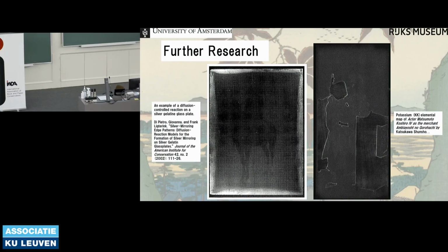Another interesting point is the actual source of the haloing pattern observed. Further testing is needed to determine what is happening. I have two hypotheses. It could be a diffusion limited reaction causing some sort of pattern similar to the one seen here on this silver gelatin print, silver gelatin glass plate. Or it could be some sort of reaction taking place with the black sumi ink that surrounds all areas of printing. Further testing is needed.